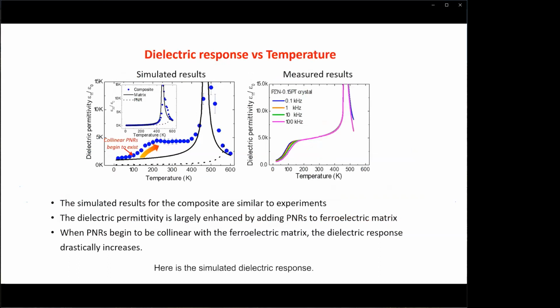Here is the simulated dielectric response. The simulated temperature dependence of dielectric permittivity is very similar to the measured results. You can see here that when polar nanoregions (PNRs) begin to be collinear in the ferroelectric matrix, the dielectric response exhibits a drastic increase, as shown here.